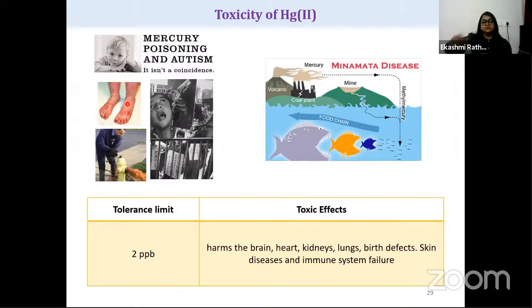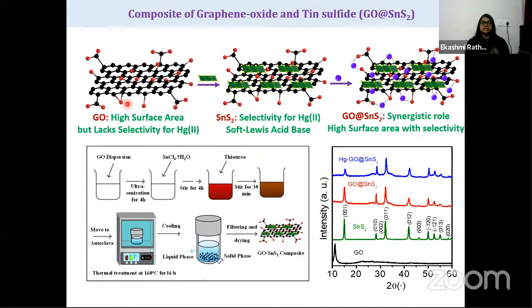So I came up with a solution, and I designed a composite of graphene oxide and tin sulfide material. Why did I use graphene oxide? The motivation was that it has high surface area. But the problem with graphene oxide is that it lacks selectivity for mercury. So to introduce this selectivity, I added tin sulfide material, which implemented selectivity in the material. Here you can see the purple ones are mercury, and they are binding and playing a synergistic role, that is, high surface area with selectivity.